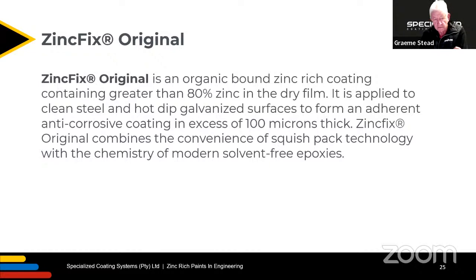So the original ZincFix packets were 3-pack with 2 seals, and it was a bit of a laborious procedure to first mix the zinc in by squidging it around into the base and then opening up the seal and letting in the curing agent. And we had a pot life of about 30 minutes, which enabled somebody to open up the packet and squeeze out the mixed zinc and apply it to the surface to be protected. Anyway, that has progressed to a 2-pack. We now disperse the zinc using new wetting agents and dispersants. We're able to squeeze more zinc into the epoxy, and the resultant is more than 80% zinc.